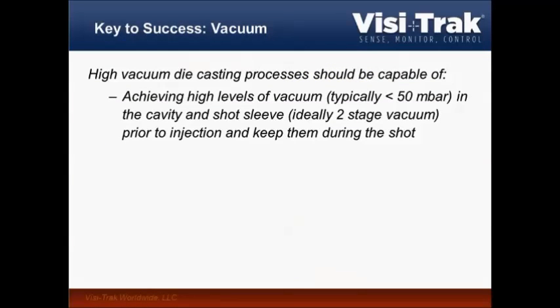So the high vacuum die casting processes need to be able to actually keep the vacuum level below 50 millibar in the cavity, which means you want to run your system probably down to about 20 millibar to make sure you actually end up with 50 millibar in the cavity. And as I said, you want to have a two-stage vacuum system where you pull vacuum both in the shot sleeve and at the top of your die prior to injection. And keep it during basically the entire shot, at least halfway through your fast shot as well.